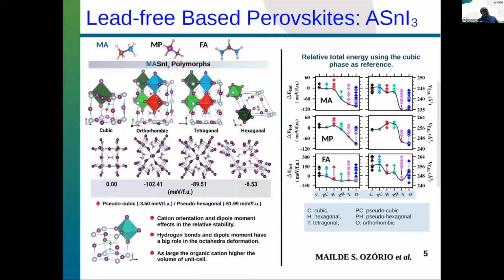And then we performed a similar study, considering now different cations, with tin iodine 3. In that particular case, this work was done by my student. Here, what we have done is consider methylammonium, methylphosphonium, formamidinium, three different types of cations, all of them have a dipole moment, which means that we try to explore different phases of the structures and really look at the role of the dipole moment. When I have a structure in which the dipole moment cancels out within the structure because you create different orientations for the molecules, in that particular case, is the energy lower? Yes, that's true. Can it affect the band gap or not? Can it affect the electronic properties or not?